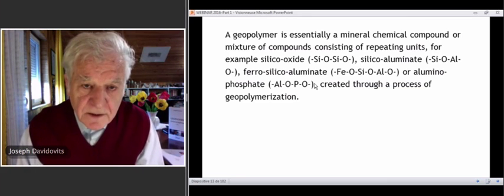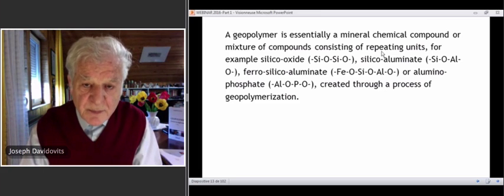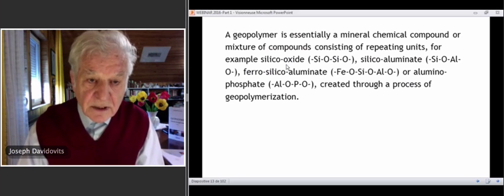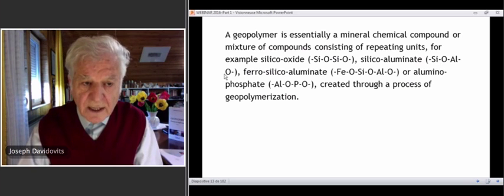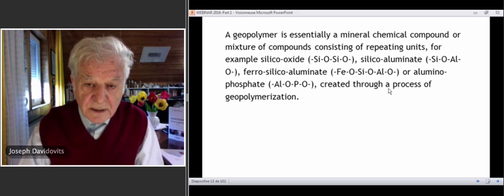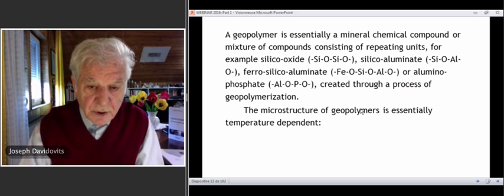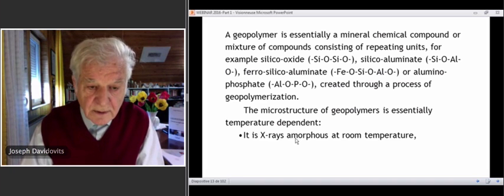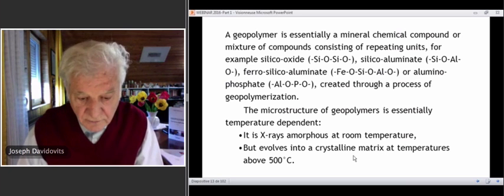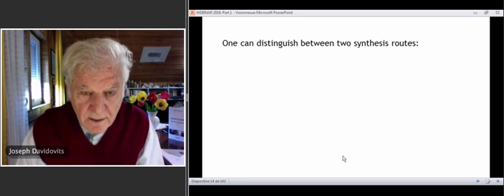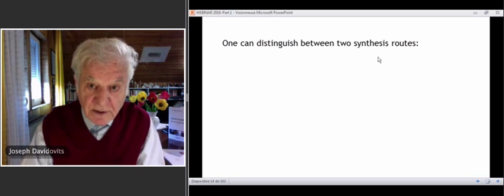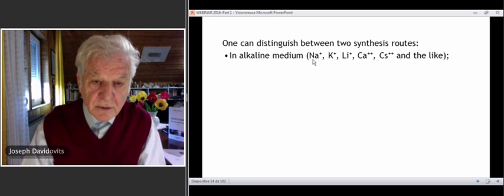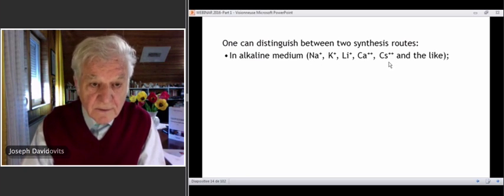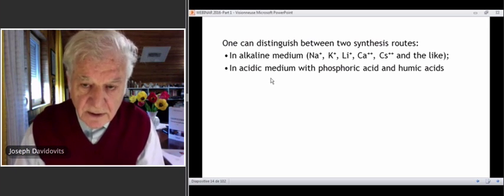So a geopolymer is essentially a mineral chemical compound or mixture of compounds consisting of repeating units. This is the definition of a polymer. For example, silicon oxide, Si-O, silicoaluminates, Si-O-Al-O, ferrosilicoaluminates, Fe-O-Si-O-Al-O, or aluminophosphate, Al-O-P-O, created through the process of geopolymerization. The microstructure of geopolymers is essentially temperature dependent. It is X-ray amorphous at room temperature, but evolves into a crystalline matrix at temperatures above 500 degrees C. One can distinguish between two synthesis routes. First, in alkaline medium, with sodium, potassium, lithium, calcium, and cesium, and the like, and second, in acidic medium, with phosphoric acid and humic acid. It works wonderfully.